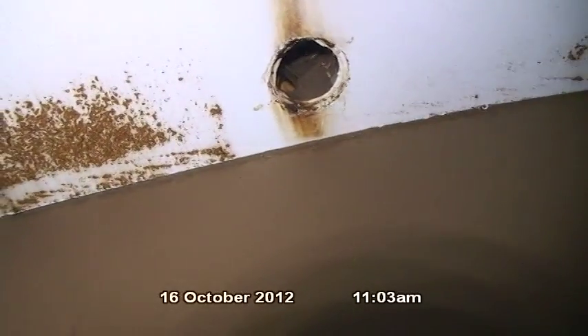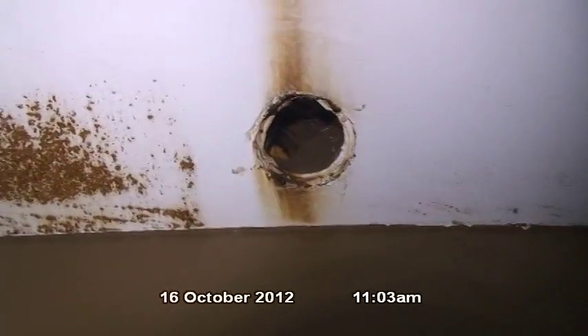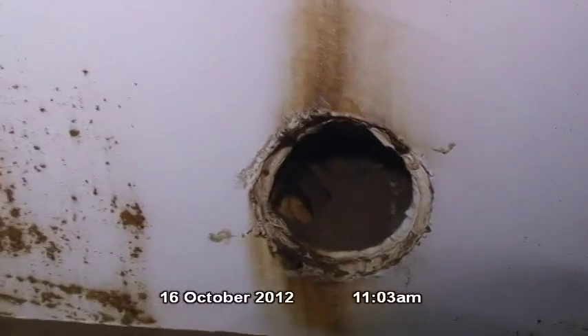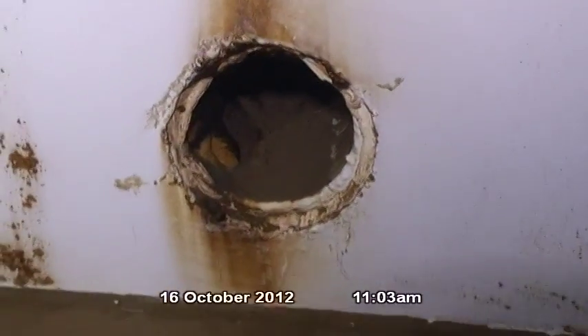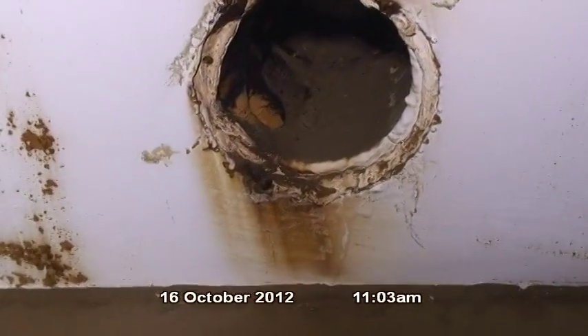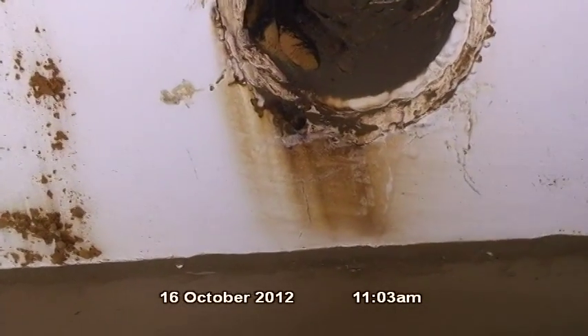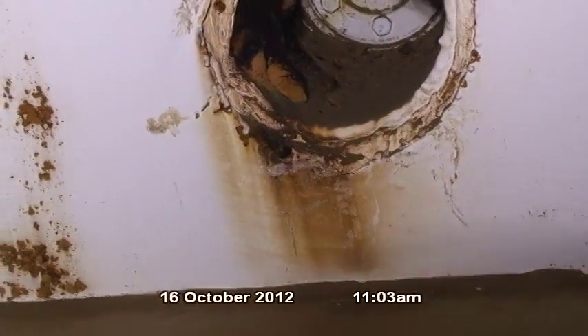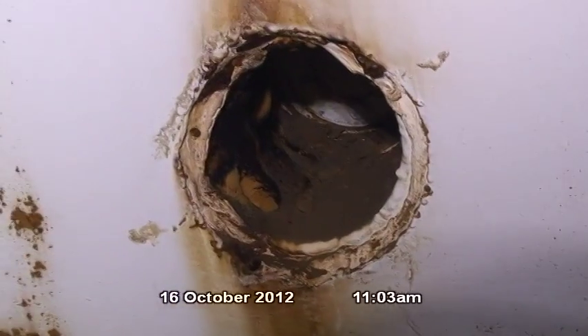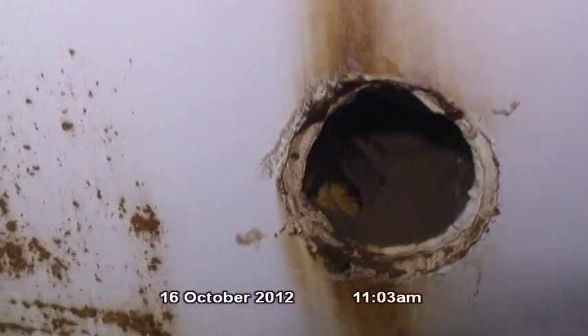The interior of the drain line is coated with epoxy. The epoxy coating is in extremely poor condition and appears to have significantly deteriorated since our last inspection in 2008. Dense corrosion is present in many areas on the interior of the drain line. Light to moderate corrosion is also present at the end of the drain line. Additional corrosion is present on the shell on ring number 4 in this area.